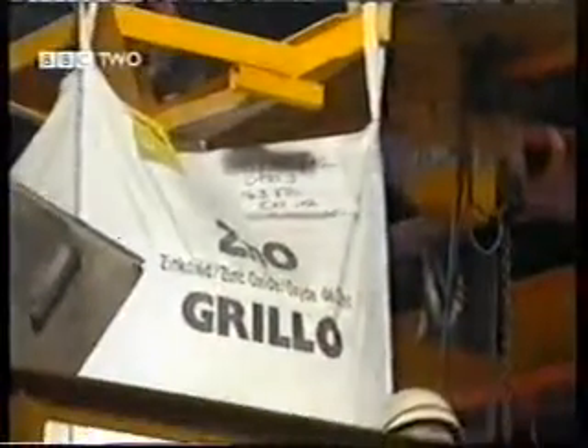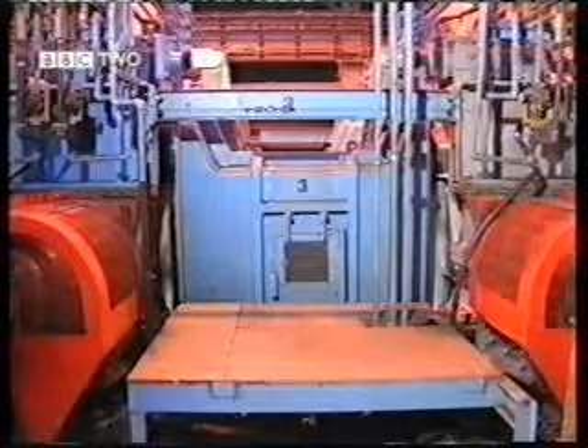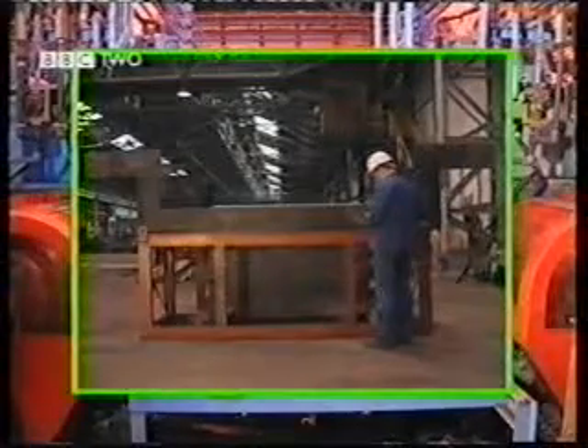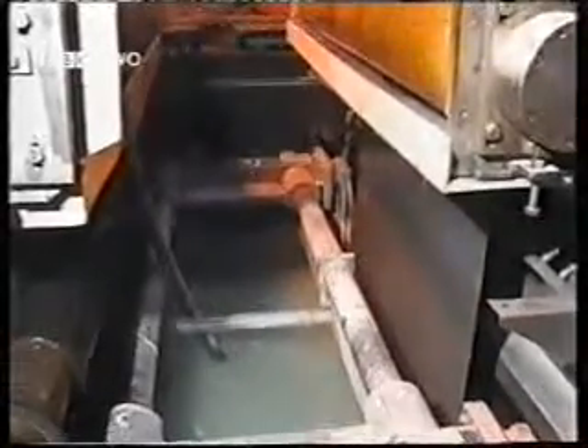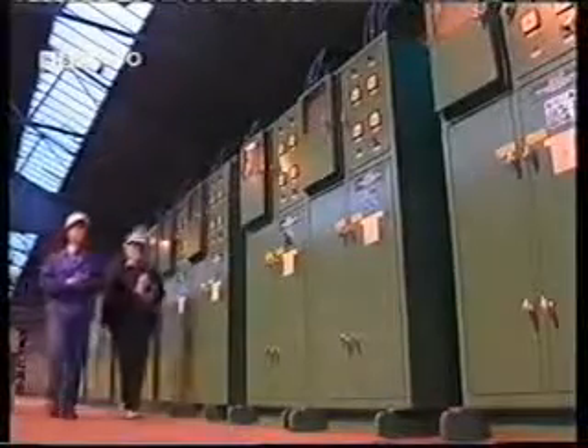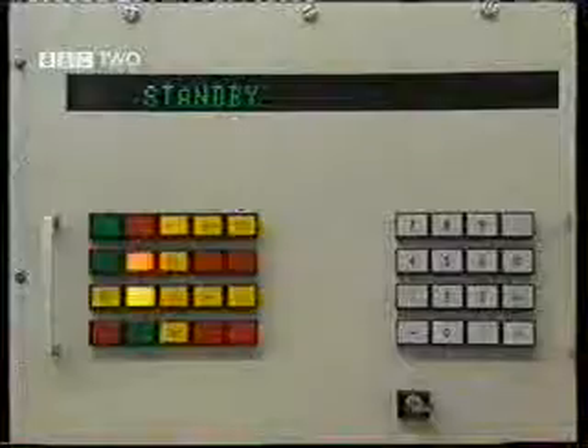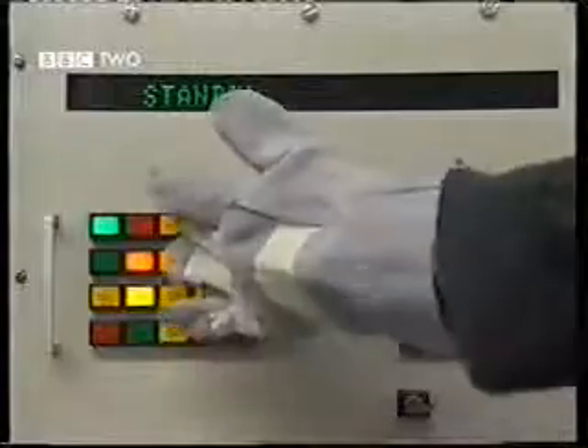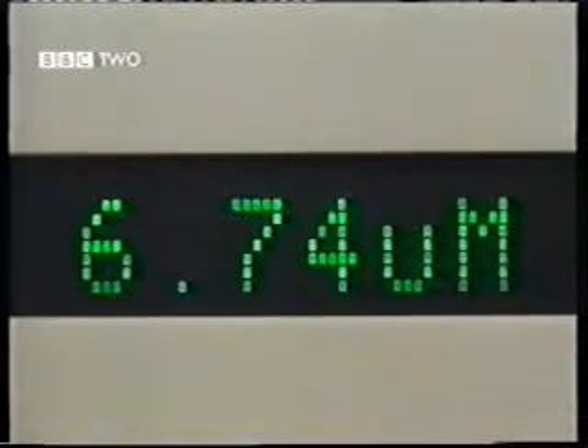Zinc supplied as an oxide is converted into zinc sulfate in a slurry with water. This plating solution, or electrolyte, is pumped to the cells continuously. Inside each cell, the huge lead alloy electrode is the anode, and the steel passing close to this is the cathode. Electrolytic deposition of the zinc onto the steel, on one surface or both, gives it a coating whose thickness depends on the electric current and time. Coating thicknesses range from 2 to 10 microns, depending upon the degree of corrosion resistance required, with 6 to 8 microns being standard within the automotive industry.